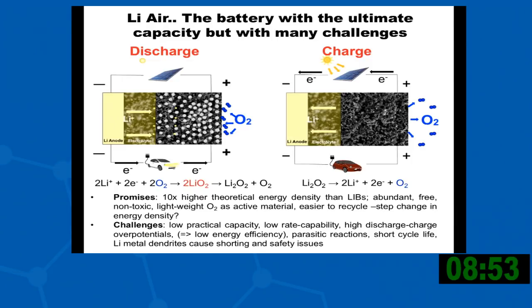And so these reactions here illustrate some of the challenges of the system. The first challenge of the system is that the intermediate between lithium and lithium peroxide is a superoxide. And so superoxide is an extremely aggressive radical, and it basically eats up any electrolyte it sees. And so there are tremendous problems of degradation of the electrolyte by the superoxide radicals. And so the carbonate electrolytes that people use in standard lithium-ion batteries are not appropriate for these systems. And then the second problem is that you form this solid product of lithium peroxide, and it's very difficult to then get rid of this on charge because it's essentially an insulator. So you've got to get the electrons to the peroxide so as to oxidize it. But because both lithium and oxygen are incredibly light, if you can get it to work, it has 10 times the theoretical energy density of lithium-ion.